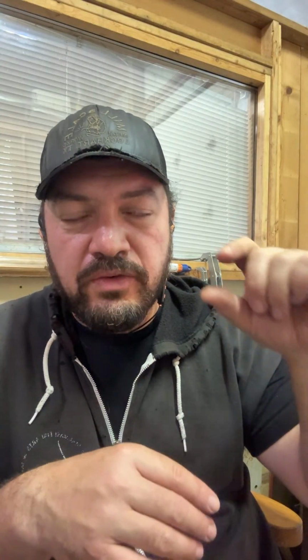It's also nice to have a little bit more length to work with in your restacks. These pieces were only like 2 3/16 long, but if I had reduced them in height by another 1/4 of an inch, that would have added at least another inch, maybe 1.5 inches to the length of each piece. I would have gotten 8 pieces out of it, but because I forged them down to 1/2 inch rather than 3/4 inch, that extra 1/4 inch of material gets essentially added onto each individual piece. Anyways, they're going to end up being longer. I'm not explaining that very well.